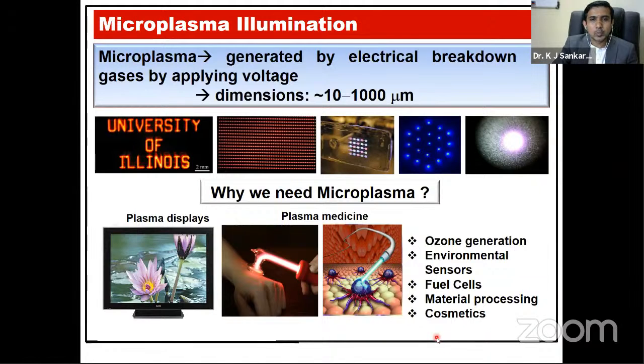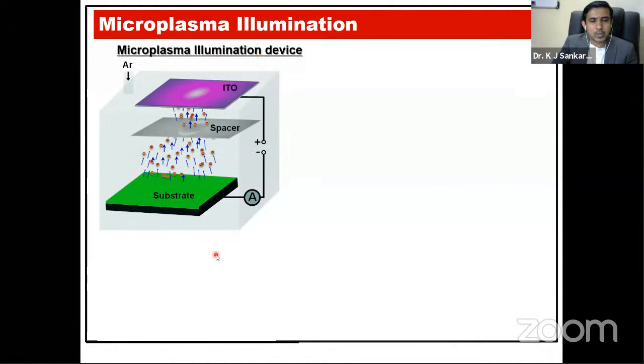So what does the microplasma illumination device look like? This is the microplasma illumination device, which, like the field electron emission device, contains an anode and a cathode. The anode is ITO coated glass and the substrate is our diamond, separated by a spacer. This complete device is placed in a vacuum system, and once at a particular pressure we pass argon gas. Once we apply the voltage, the primary electrons from the substrate get emitted and react with the argon gas, which emits secondary electrons. The argon ions make the plasma over here, which can be viewed through the ITO coated glass, because ITO coated glass is transparent, and then the secondary electrons are collected.